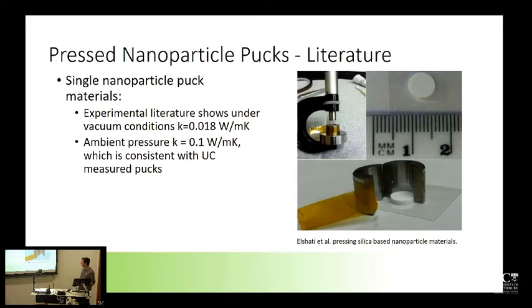Looking around a little more, I found some literature on pure nanoparticle pucks, or uncomposite versions of it. They found some interesting results, namely when they were under vacuum conditions, they had similar results, on the same order of magnitude as other literature, in the tens of milliwatts per meter Kelvin thermal conductivity. Whereas at ambient pressure, they had 0.1, or 100 milliwatts per meter Kelvin, which is very similar to what I have. So one of the next tests I really want to do is to put these pucks into a vacuum chamber and see how much it changes, or see if I get numbers that are similar to that at all.